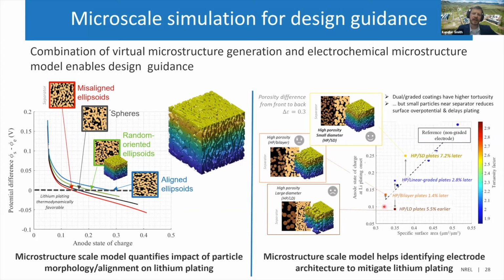And as you go to higher surface area, that also delays the onset of lithium plating. So as we go up and to the right, that's higher specific surface area and delayed onset of lithium plating. He's looked at a lot of dual coatings, or you could also do this with a graded coating where you've got a different porosity close to the current collector versus close to the separator.